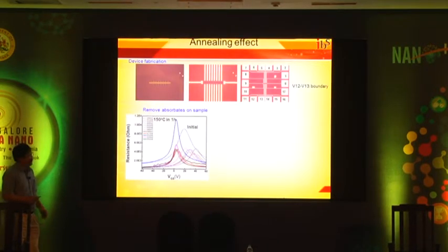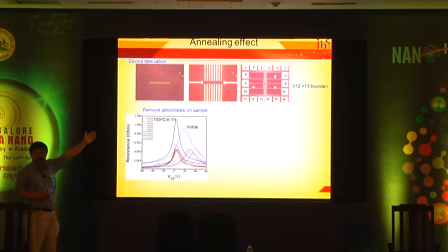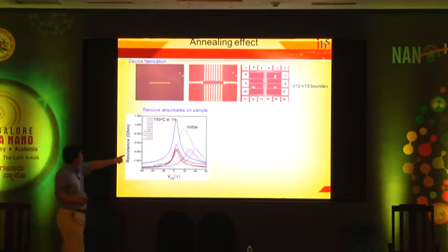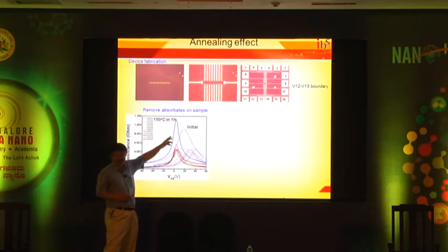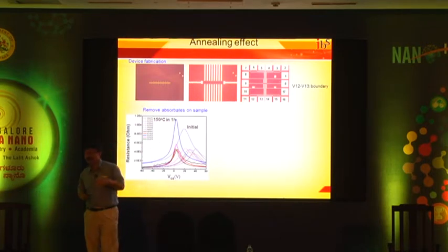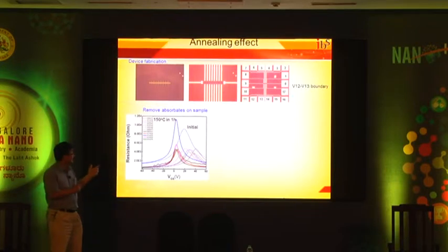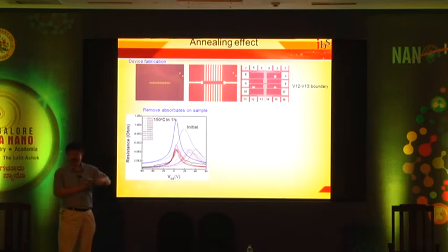Now, of course, at some point we need to determine the resistance at the grain boundary precisely. In this case, we have to make a multi-electrode near the grain boundary. And between number 12 and 13, we do have this grain boundary. So you can see at the grain boundary, the resistance is very high. Although this grain boundary is influenced by different chemicals, even though you try to remove these chemicals, the resistance is still high.